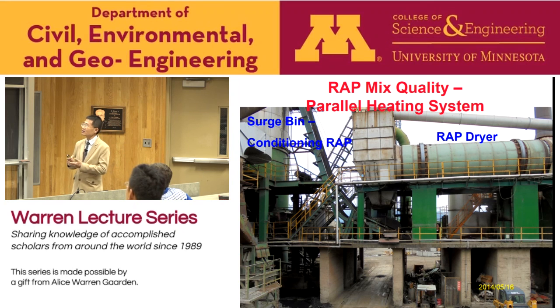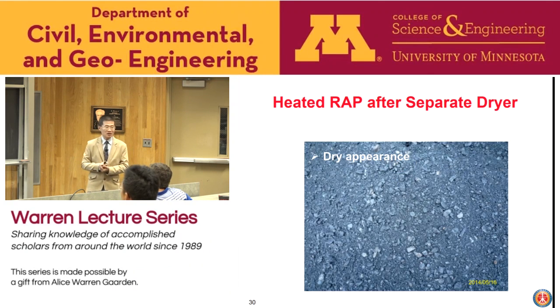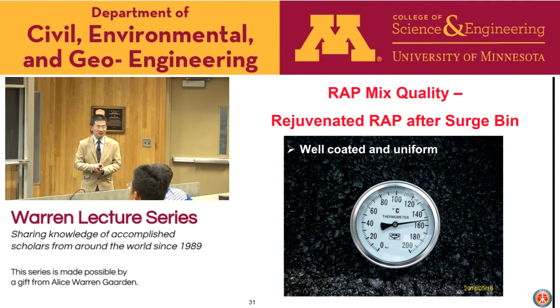for about 2 hours in our study. The merit of conditioning the RAP material is that it allows the rejuvenator to diffuse into the aged asphalt in the asphalt plant. This photo shows the heated RAP materials after the RAP dryer. This heated RAP had a dry appearance and acts like black rock, just like black rock actually is. We don't have an interaction yet, as we can see here. And this photo shows the rejuvenated RAP materials after conditioning for 2 hours.